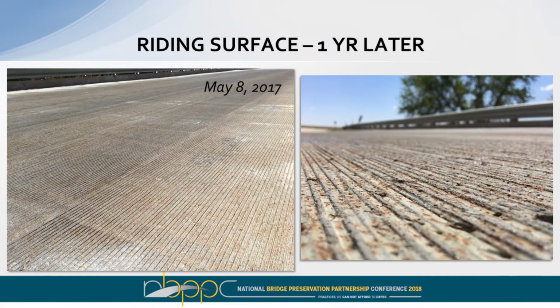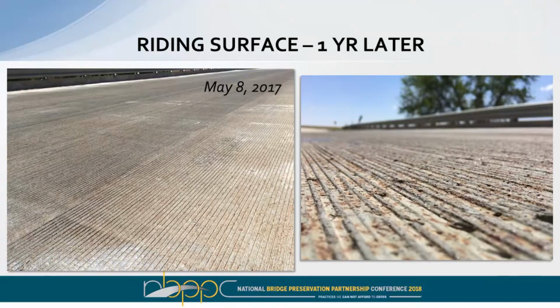And this is what the riding surface looked like about a year later after the job had been done. So you'll see kind of an orangish hue to the deck. So during that milling process, you do expose a little bit of those steel fibers, and whatever has been exposed will kind of corrode off the surface. But on the right-hand side, you can see that any fibers that were sticking up have disappeared. They've just kind of left behind a nice historic-looking corroded surface there.